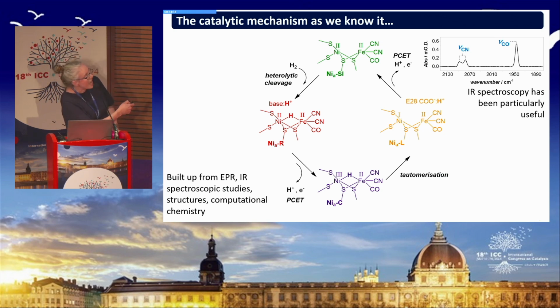And then finally, another proton-coupled electron transfer step removes the proton off the active site and reoxidizes the nickel back up to the nickel 2 level, ready to start the catalytic cycle again. And our insight into this catalytic cycle has been built up from a mixture of EPR and infrared spectroscopic studies in particular, as well as X-ray diffraction structures and computational work.